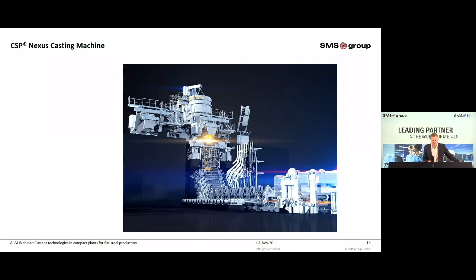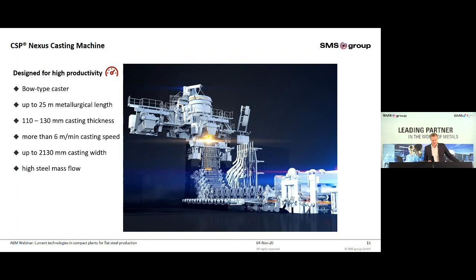Now, I would like to fly with you through the Nexus plant, beginning with a high throughput casting machine. The bow-type caster has a length of up to 25 meters, a casting thickness range from 110 to 130 millimeters, a casting speed of more than 6 meters per minute, and a casting width of 2,130 millimeters, which ends up in a high level of steel mass flow.